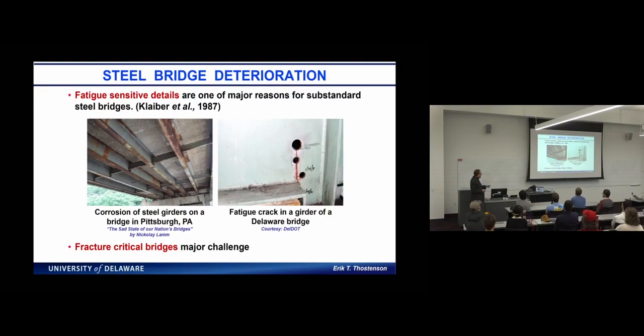Yeah. But one of the things you can see here, this crack was growing and the first crack stop hole didn't work. So they drilled another one. And for fracture critical bridges, they actually replaced this whole bridge recently. But these fracture critical bridges are a major challenge. And this is also where you see corrosion.